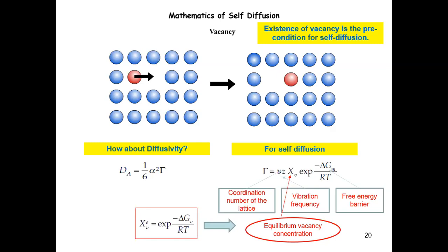And if you put the atom away from the system to infinity, because you do the work, you basically create a vacancy. When the atom that you pull out is very far away from the material, you can consider it an independent atom, and in the material you've created a vacancy. But during this process, you do work, and that work adds energy to the system. That work is basically the activation energy to create a single vacancy. Does this make sense to everyone? Okay, so this is where you have the activation energy for the vacancy.